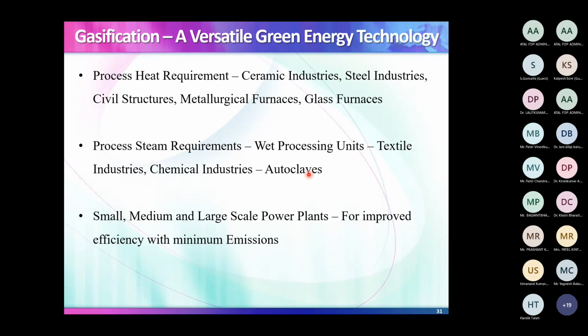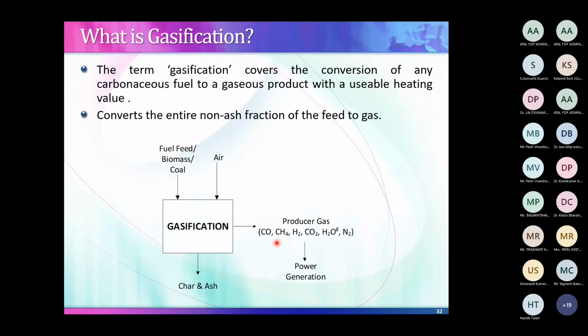Now, what is gasification? The term gasification covers the conversion of any carbonaceous fuel to a gaseous product with a usable heating value. And what it does, it converts the entire non-ash fraction of the feed to gas. So this is my feed. There is a gasifier. I supply partial air. You will produce here the producer gas, this is its composition, and some char and ash will come out. That means this will not go to the boiler, so no erosion, nothing. And this gas you can use for power generation.